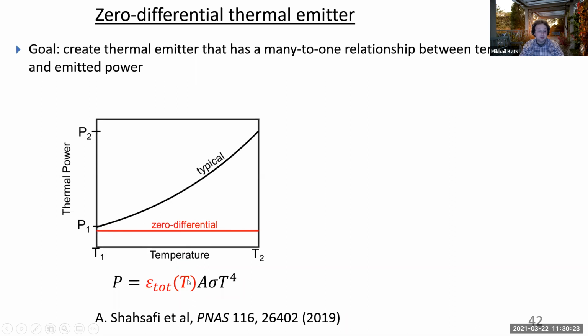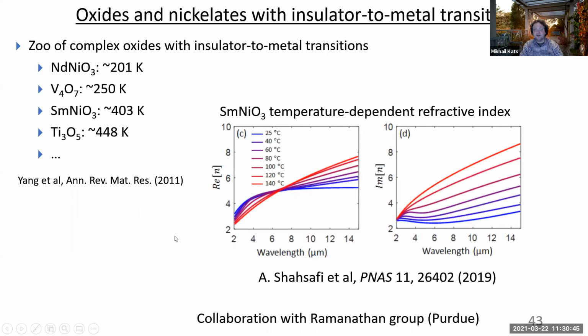The way to do that, in terms of the Stefan-Boltzmann law, is to have an emissivity which decreases as temperature to the fourth, right? So this should have something like T to the -4, so that the whole thing ends up being a constant. Fortunately, we were able to implement this in 2019 in this paper in PNAS, based on another material with an insulator to metal phase transition. In this case, we're using a rare earth nickelate, samarium nickel oxide, which has a very complicated insulator to metal phase transition at around 100 to 130 degrees Celsius.